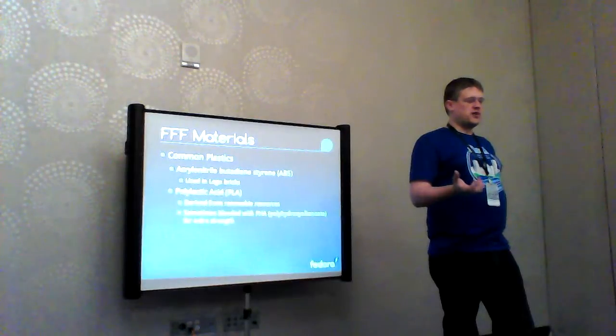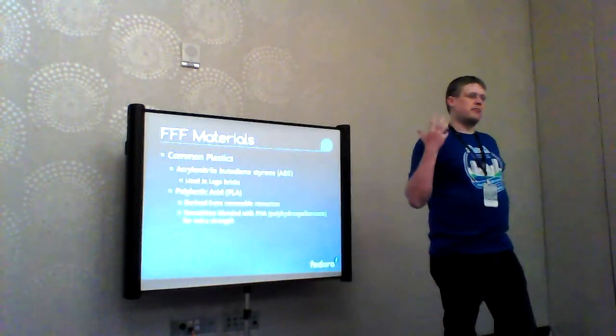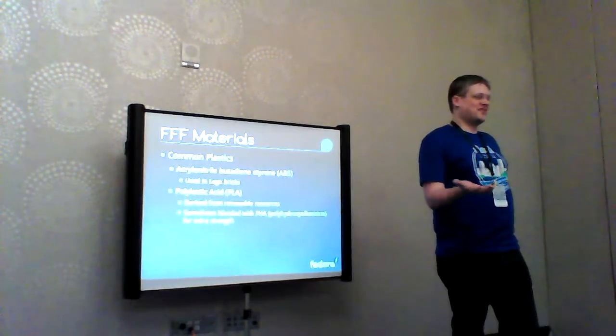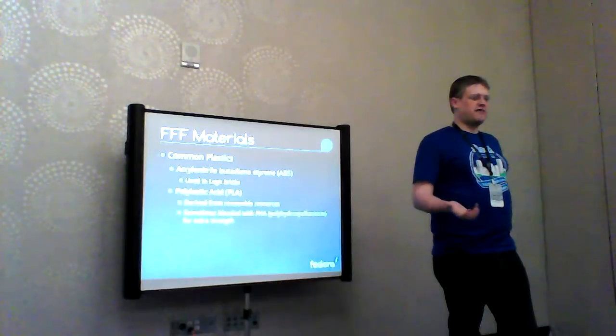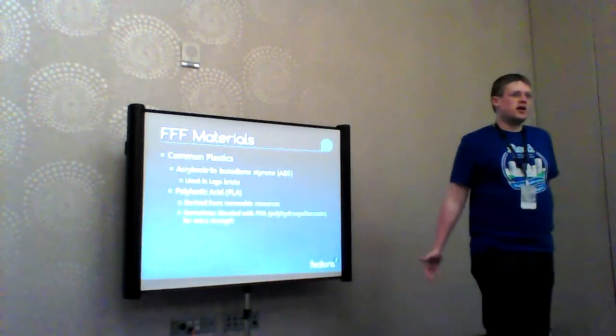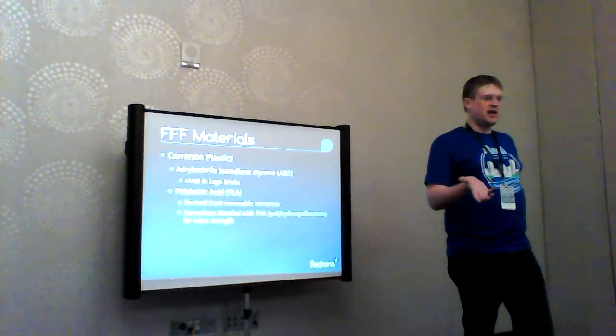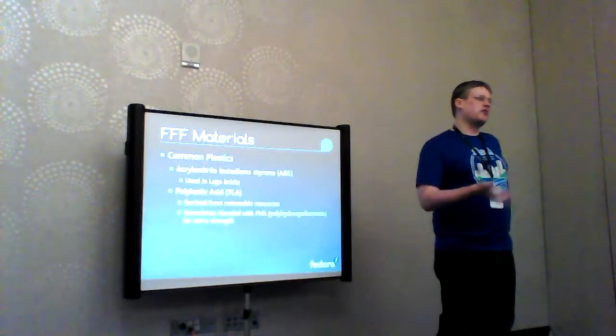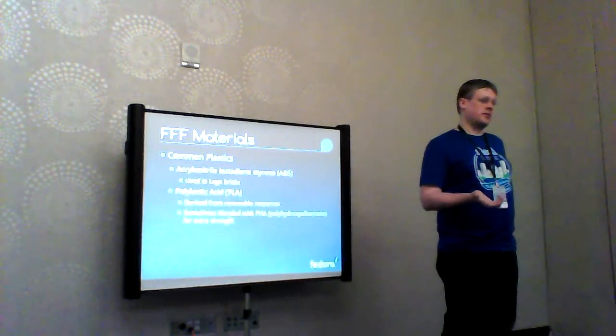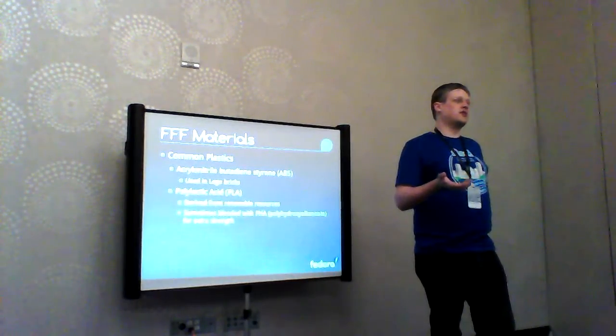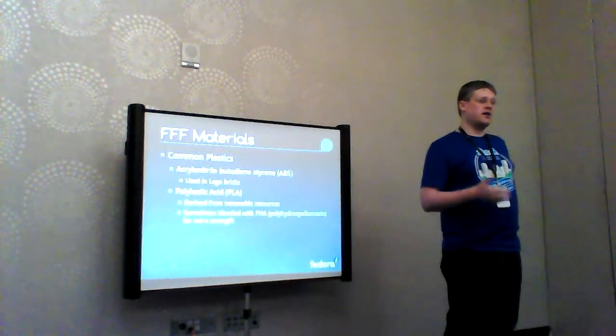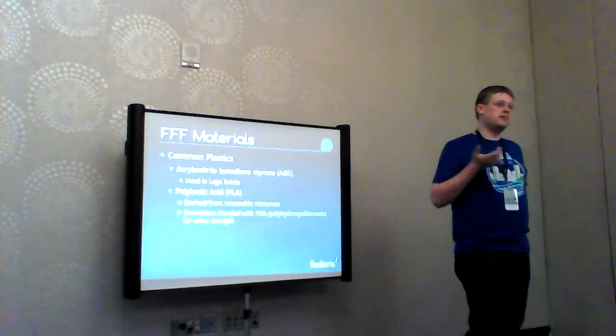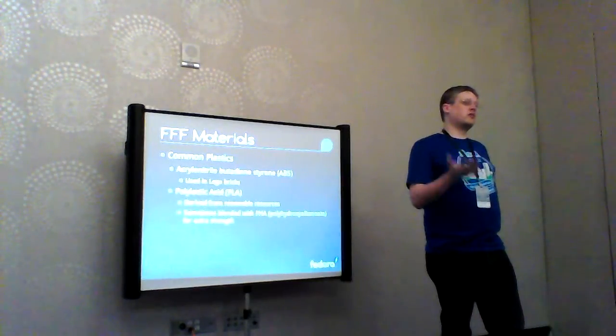Another option is PLA — polylactic acid. PLA is biodegradable, bio-friendly, and derived from renewable resources rather than oil. It smells like pancakes when printing. Some people mix it with PHA — polyhydroxyalkanoate — which is also biodegradable, and mixing it with PLA improves its strength, getting it closer to ABS. PLA's melting point is slightly less than ABS, and it can be printed on printers without a heated bed, though a heated bed at low temperature gives better results.